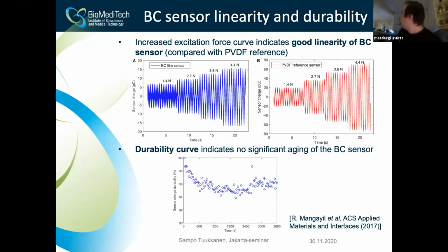Okay, and for these bacterial cellulose films, we also measured with different forces, like increasing the force. First we had 1.4 Newton force, and then we increased it a little bit, and we saw the increasing output. I don't have a plot here for the curve, but basically with these points you can make the linearity curve as well, but I don't have it here.